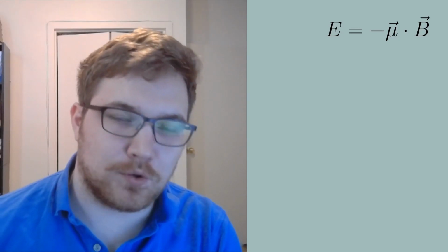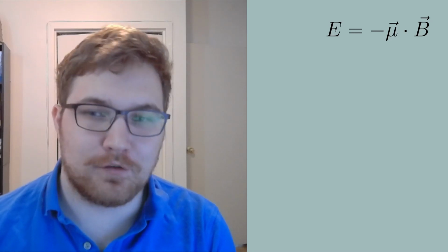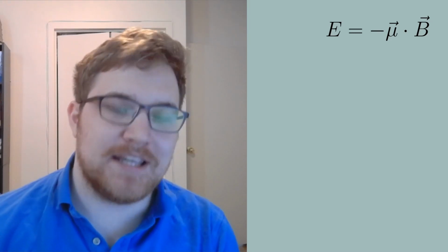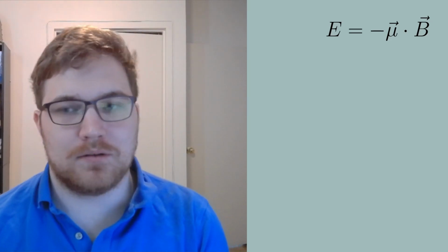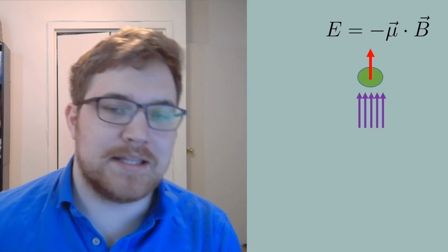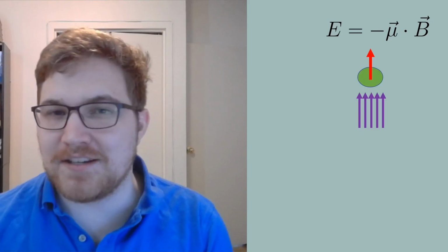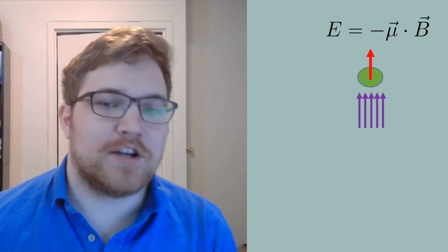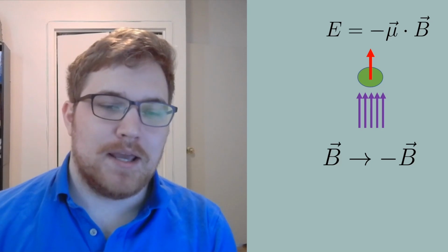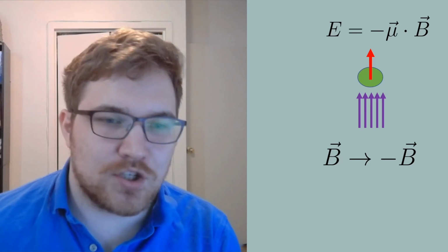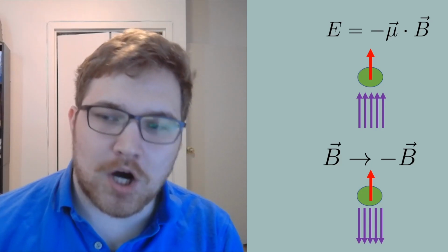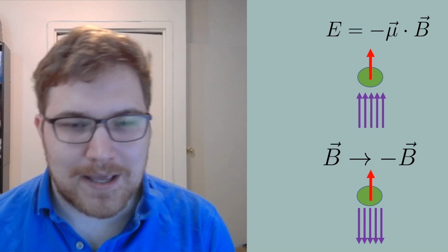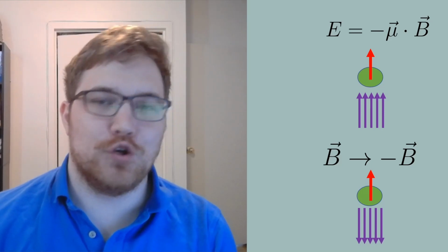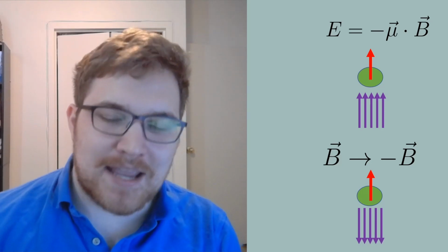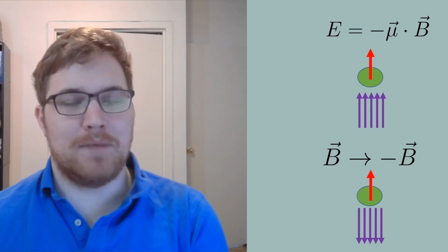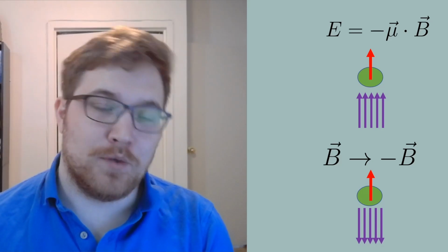First, we prepare our lithium fluoride at a low temperature in a strong magnetic field. This allows us to write the energy effectively as the interaction of the field with the magnetic moment. Each proton's magnetic moment is then in the direction of the magnetic field, or at least most of them are. We then reverse the direction of the magnetic field very rapidly. If the switch was quick enough, the magnetic moment doesn't change its direction and is now in the opposite direction of the new magnetic field. This then corresponds to a higher energy state for the nuclear spins, since the magnetic moment is anti-parallel with the field, or at least most of the magnetic moments are anti-parallel with the magnetic field.